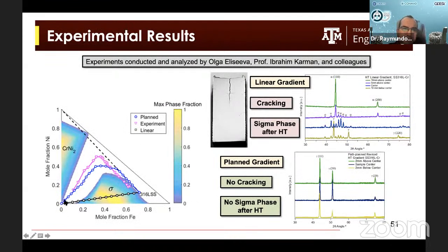So this is what we did. This is what you get in a linear path. And this is what you can get if you plan the path. And then we did the experiment with a multi-material DED. It turns out that it is very difficult to do multi-material printing. You actually have to calibrate the feeding rate and test it and validate your calibration curves significantly. And this was the first attempt. Now we are getting better at calibrating the feed rates of the multi-material printer. And we can get within 1 to 2 atomic percent in terms of the composition that we want to print versus the composition that we actually print.